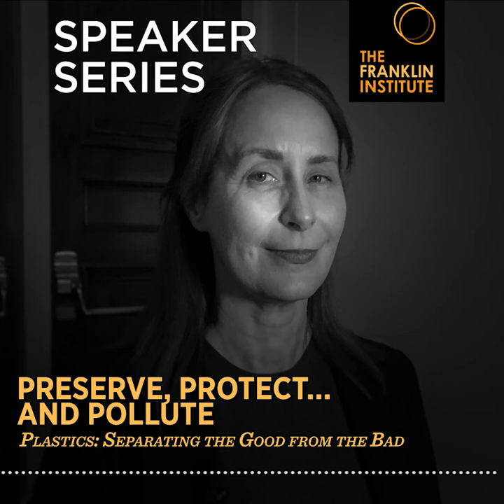Polyethylene is prized for its stretchiness — it can give quite a great deal before it breaks. So thin films such as saran wrap and plastic bags are prized for this property. Higher density polyethylene can hold heavier materials and is often used to contain chemical substances, such as detergent bottles. We can make a very simple change to the polyethylene chain by substituting one of those hydrogen atoms with a chlorine atom. A simple change like this results in the production of polyvinyl chloride, or PVC. This material produces something that's much more dense, much more rigid — it's prized in construction materials and many of our plumbing systems.